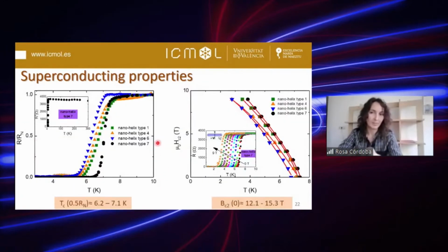And interestingly, we observed that the main superconducting properties, the critical superconducting temperature and the upper critical magnetic field, were very similar for all of them. And it was very similar also to the values obtained for hollow nanowires already studied. So this is giving us an idea of how robust the superconducting properties of these nanohelices are, with completely different three-dimensional geometry.